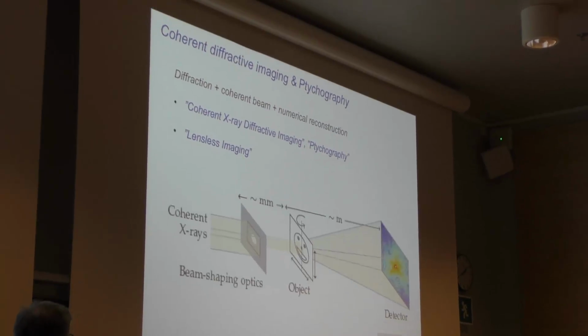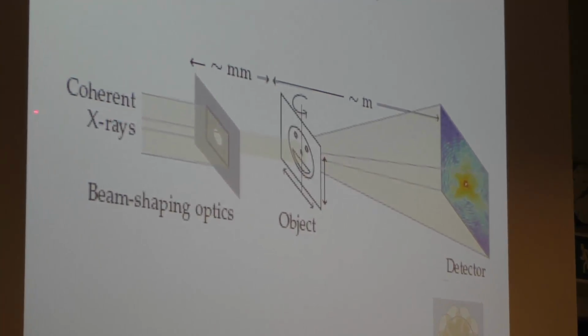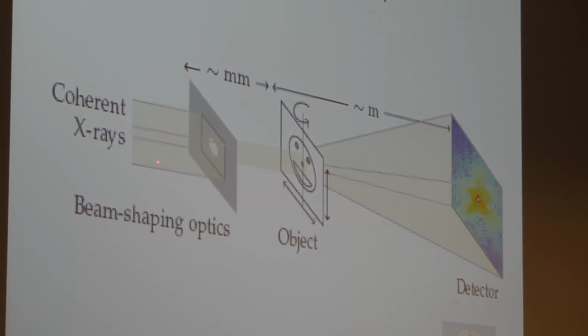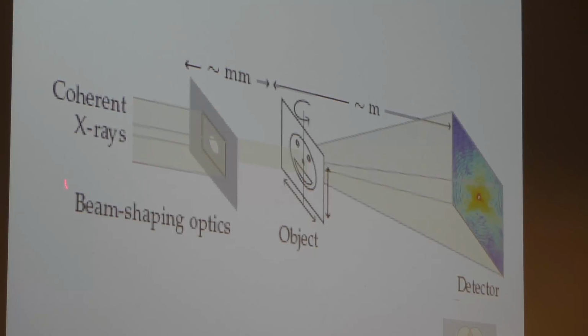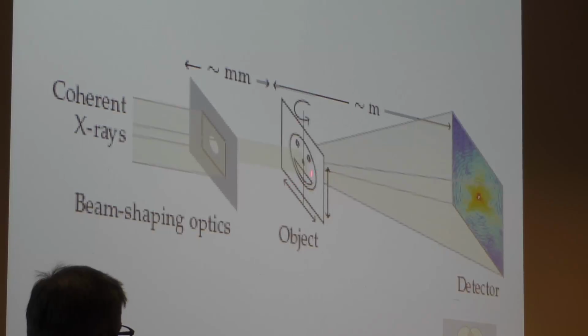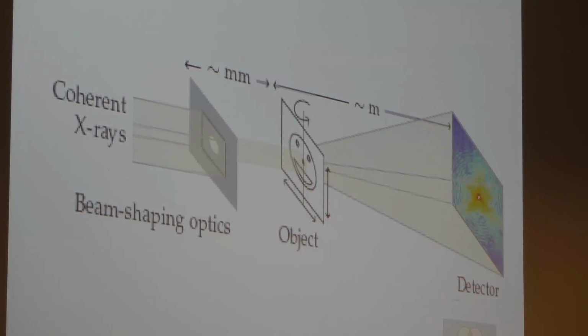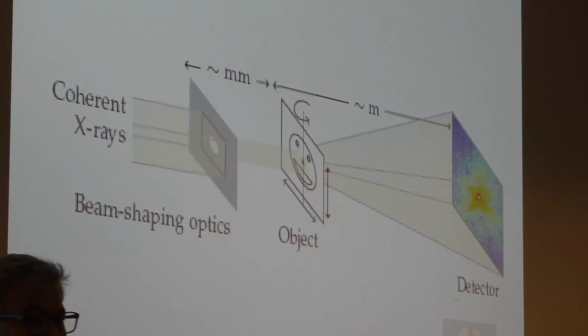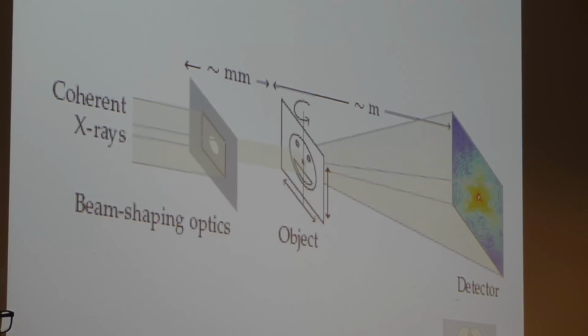So how is this used for imaging? Well, one uses such a beam of coherent X-rays, and to find this you have to go to specialized synchrotron beam lines. This coherent X-ray field is shone onto the substrate, onto the object, and then whereas in a traditional imaging setup you would have had an objective lens here so that you would get an image on your detector, right? But in the coherent diffraction technique, instead of detecting the image, we are detecting the scattering patterns, and then using a set of iterative numerical techniques, one can actually, from a set of diffraction patterns, calculate what the object looks like to high resolution.